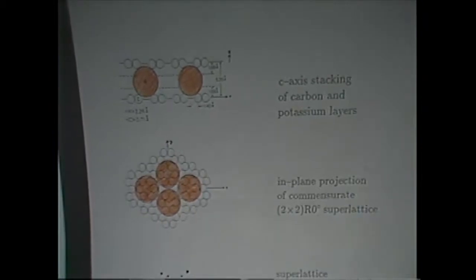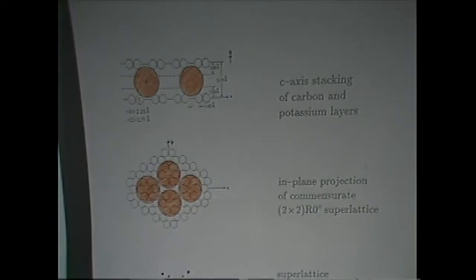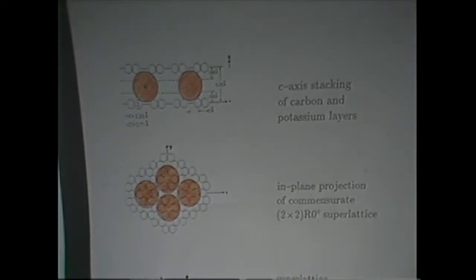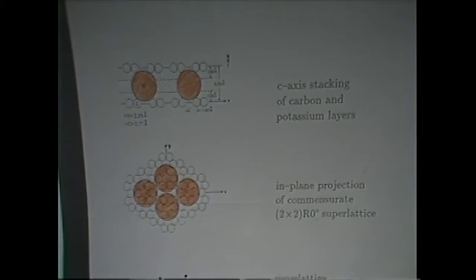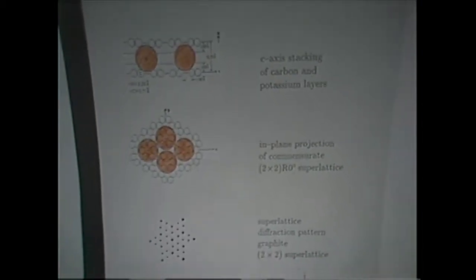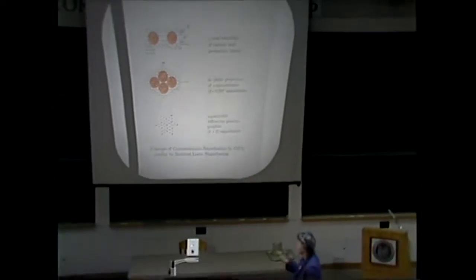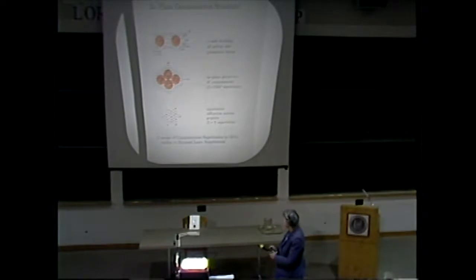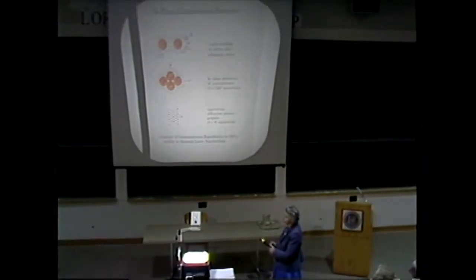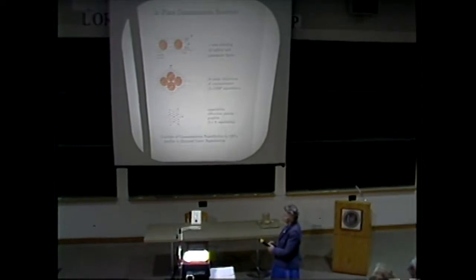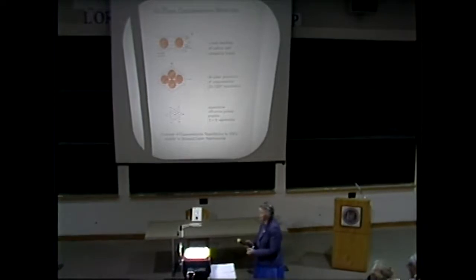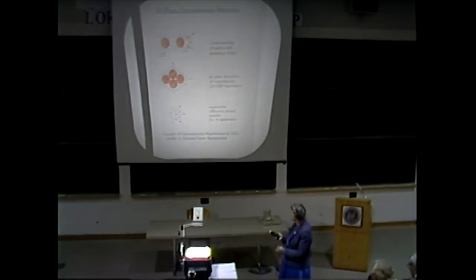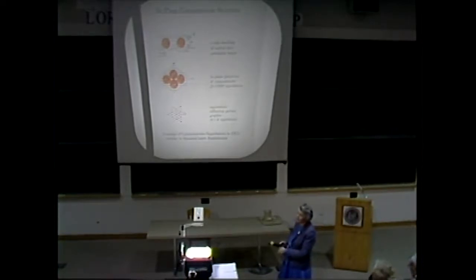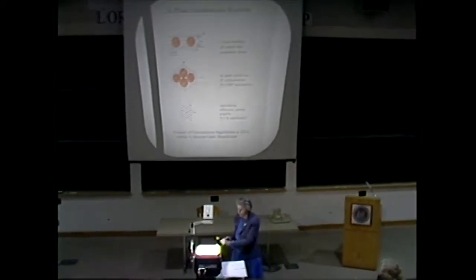However, we have one modulation feature, and that's the graphite, which makes the intercalate want to sit over the hollow of the honeycomb structure of the graphite lattice, because by doing so, we can pack the three-dimensional crystal and make a closer packing than any other way. So just by these geometrical arguments, you could see that there are two things acting. One is the interatomic forces, and the other is the attraction to the graphite honeycomb lattice. And in this case, with very small space from the closest packing of the intercalant, we can achieve registry with the graphite, so it likes to do that, and in fact does so in the stage 1 compound. And to prove that we have that, you do a diffraction pattern, and that's a pretty diffraction pattern. I had to draw it for you to show you the diffraction pattern for a 2 by 2 superlattice.